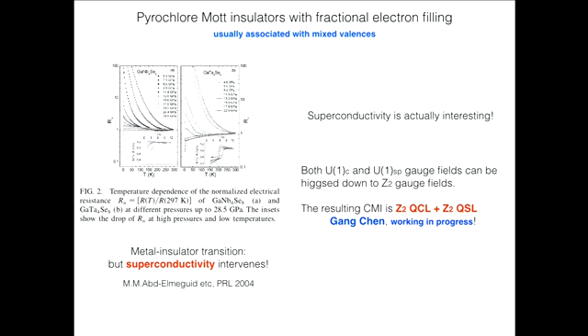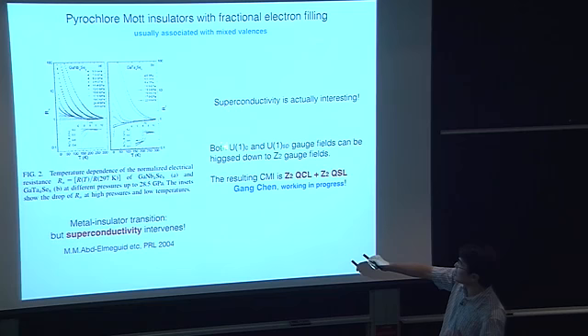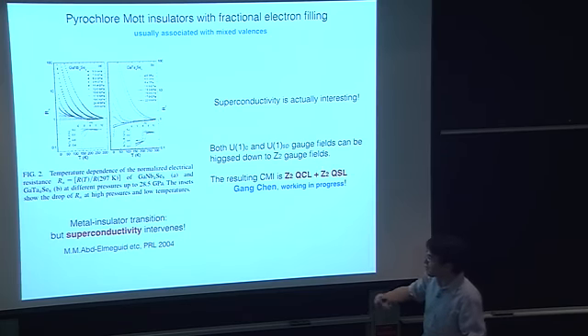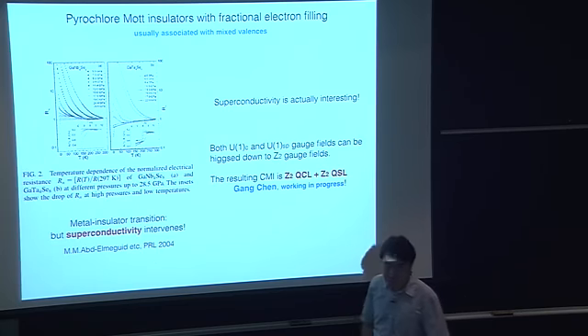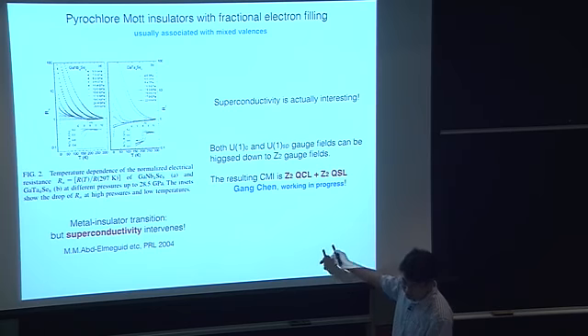In fact, the real material is a superconductor actually. So the proximate metallic phase is a superconductor. So actually superconductivity is very interesting. If it is a superconductor, there is some interesting possibility that both the U(1) charge sector gauge field and the U(1) spinon sector gauge field can both be Higgsed down to Z2 gauge fields, instead of just the continuous part being Higgsed in the Mott insulating phase. So the resulting cluster Mott insulator can be a Z2 quantum charge liquid plus a Z2 quantum spin liquid in 3+1 dimensions. So this is the one direction I'm pursuing right now.